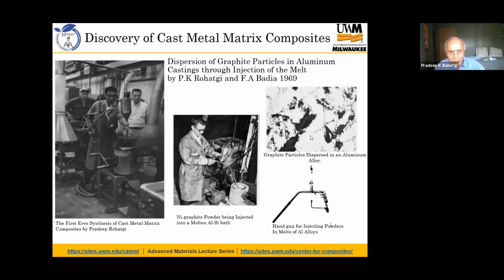So this is a slide of the original discovery with my colleague. This is myself, F.A. Badia, and what we had done for the first time, introduced nickel-coated graphite particles in aluminum and solidified the melt. This was published in 1969, about 50 years ago. And we produced a microstructure where these black graphite particles are dispersed in the matrix of aluminum. So this was the first example of a synthetically produced cast metal matrix composite between two immiscible materials. I will later get back to this kind of microstructure.